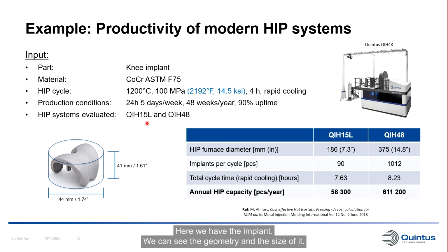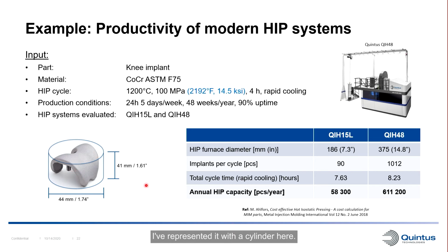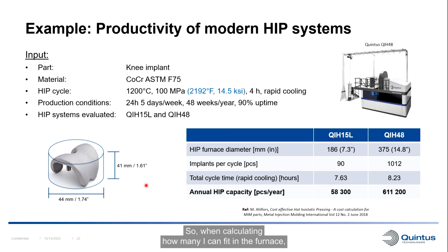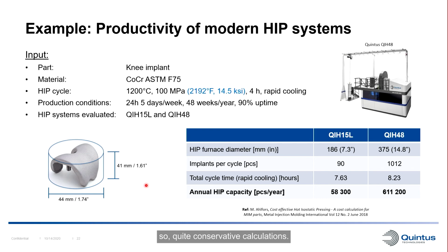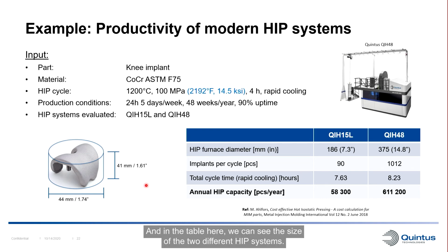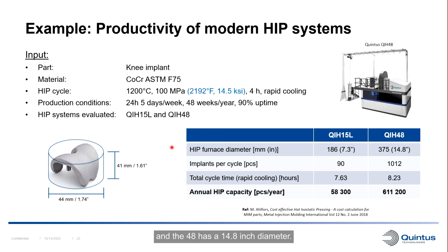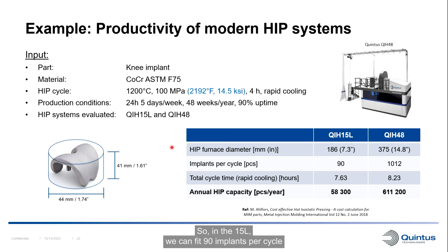Here we have the implant. We can see the geometry and the size of it. I've represented it with a cylinder here. So when calculating how many I can fit in the furnace, I assume that they're not touching each other, so quite conservative calculations. And in the table here, we can see the size of the 2 different HIP systems. So the 15L has a 7.3-inch diameter of the hot zone of the HIP furnace, and the 48 has a 14.8-inch diameter. So in the 15L, we can fit 90 implants per cycle, and in the 48, we are just above 1,000 implants per cycle.